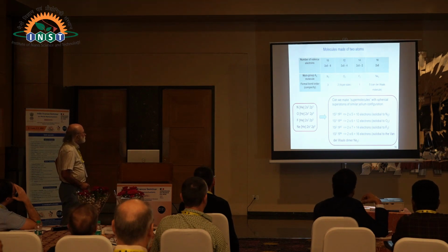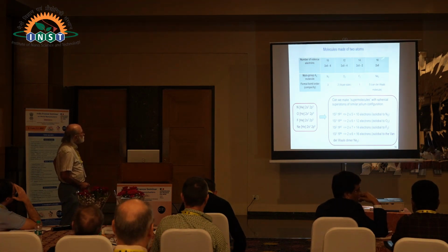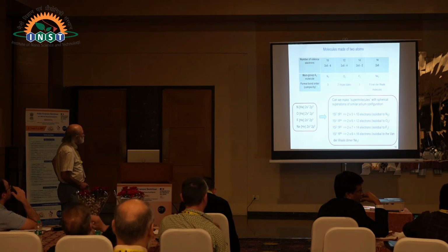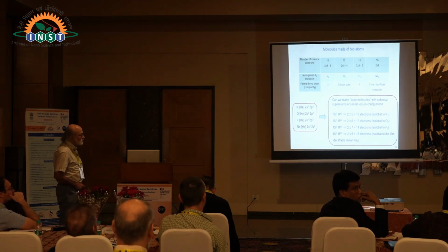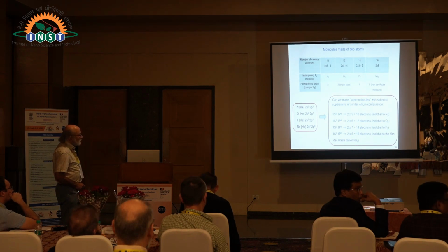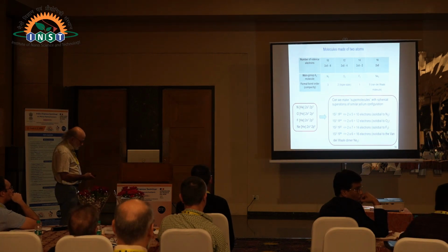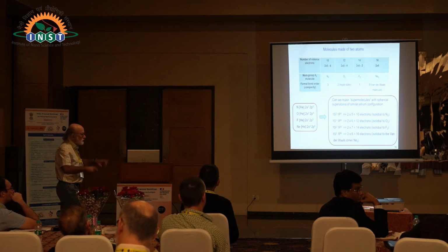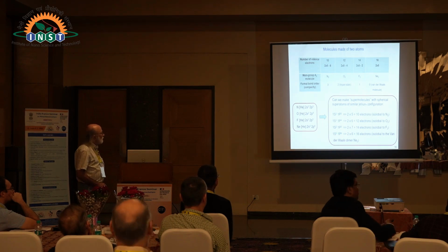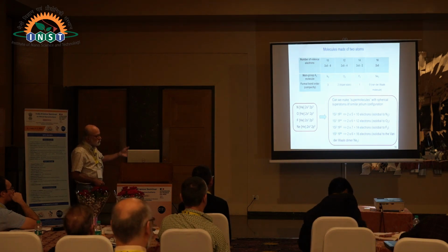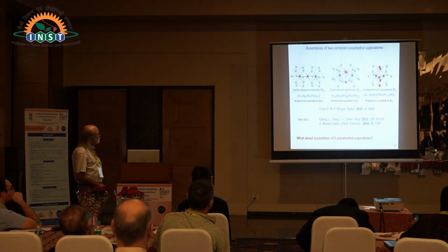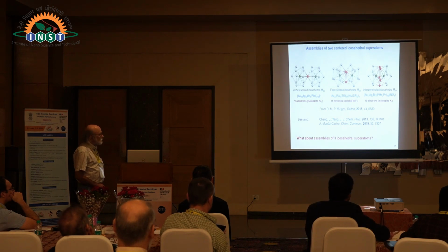So each time you are making a bond, you are removing 2 electrons, 1 bond, another bond, another bond. So we go from 16 to 10, like that. It depends on the bond. The electron count depends on the bond order, and I will say on the compacity later. So the question is, can we make the same thing with 2 icosahedral superatoms and make molecules which are isoelectronic, isolobal, equivalent to superatomic molecules? Actually, the answer is already in the literature.